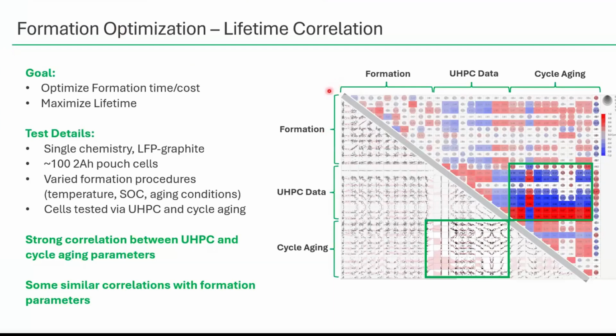This is a correlation matrix dimensionally reducing the data and looking at individual formation metrics such as efficiency, discharge capacity, charge capacity, the UHPC metrics such as the final average coulombic efficiency or the final slippage value during UHPC testing, and then the cycle aging parameters like number of cycles to 80%. Looking at all these metrics and how they correlate with each other, we can see some very strong correlations between the UHPC cycling metrics and how the cells performed in cycle aging.